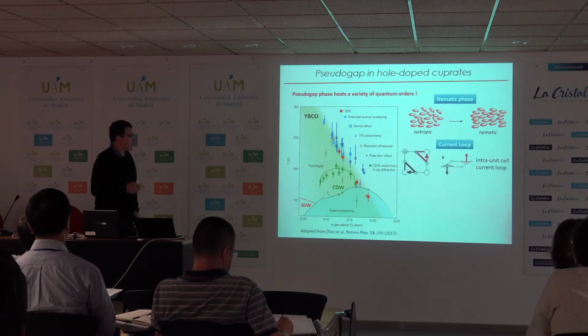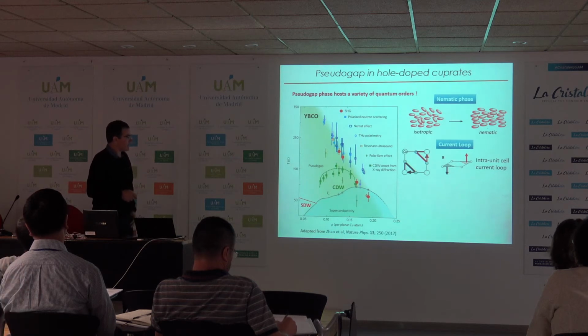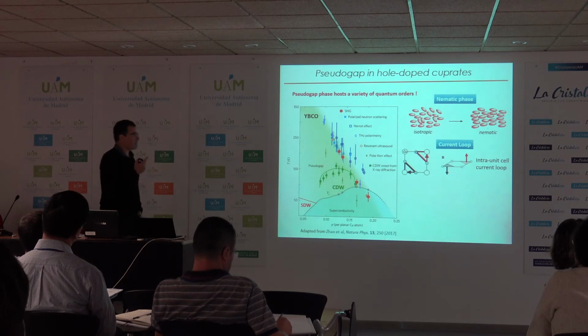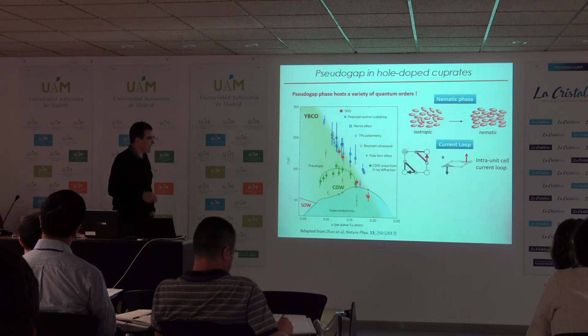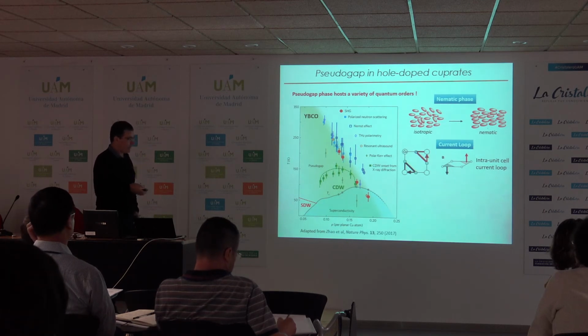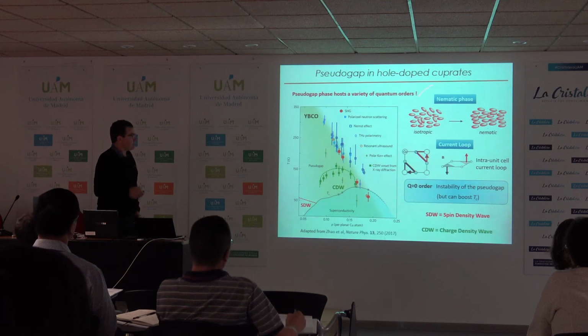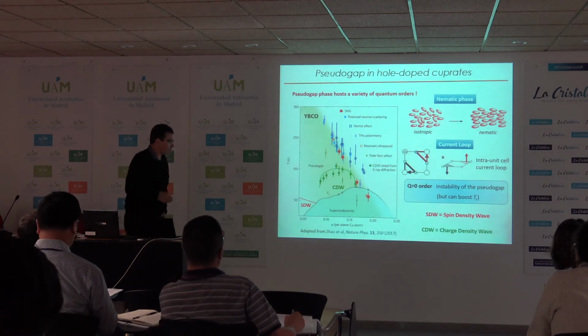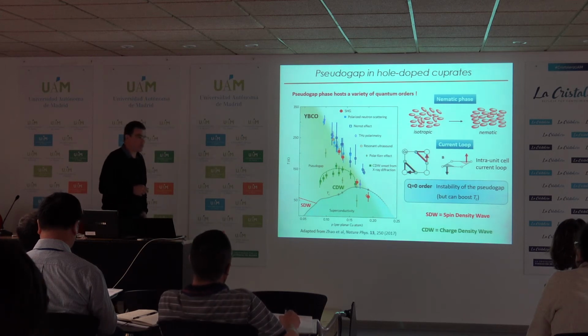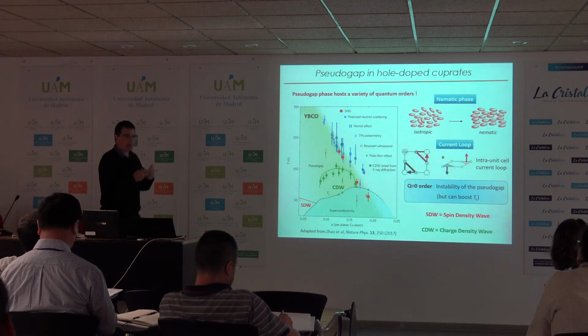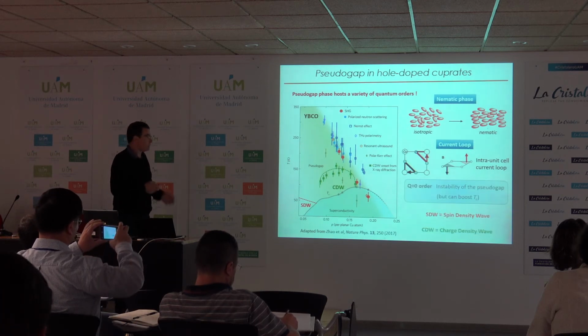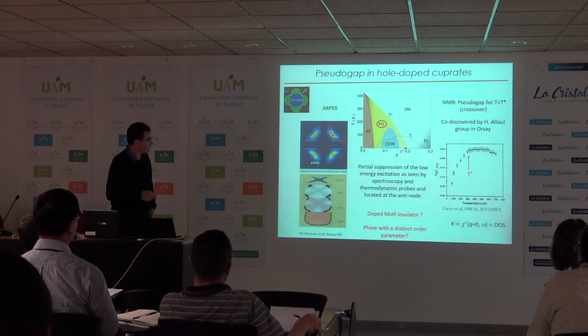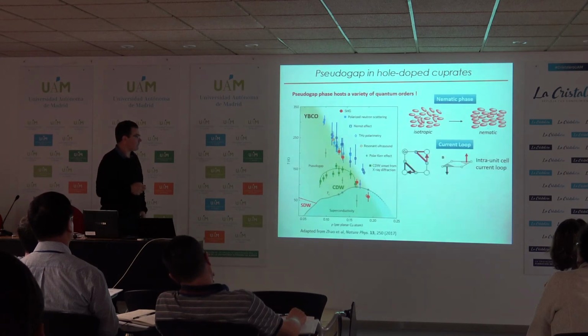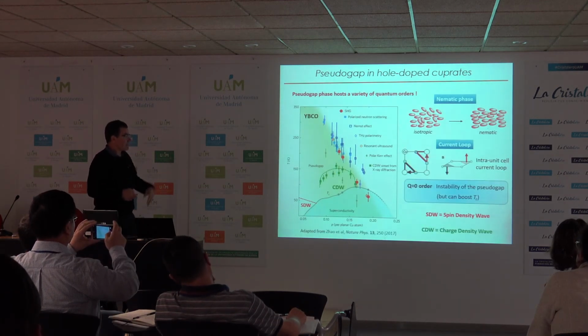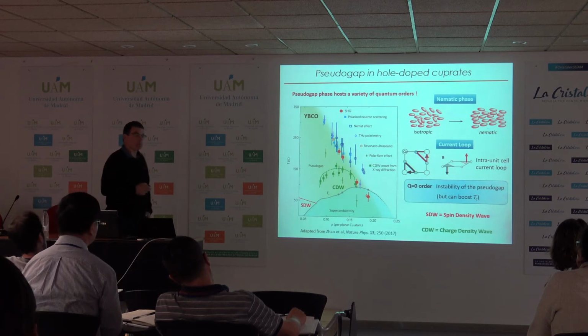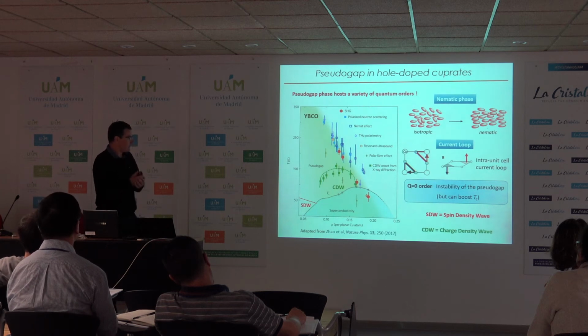From a neutron measurement, some claim that this phase corresponds to a current loop, an intra-unit cell current loop antiferromagnetic phase. This is the model of Varma. But these two models are compared to other Q equals 0 orders, meaning that there is no opening of a gap. And this cannot explain directly why we see this phenomenon that I have discussed before, a partial opening of the gap at the antinode. But of course, this instability of the pseudogap can boost Tc, as has been discussed by many theorists.